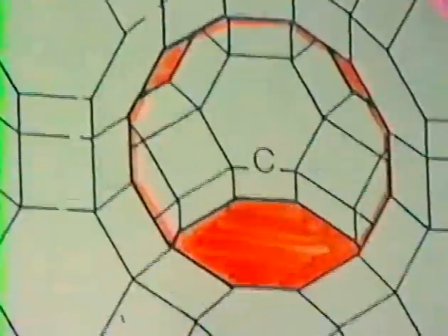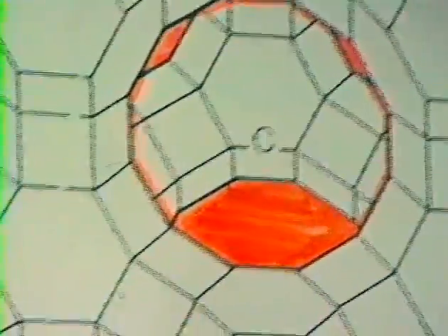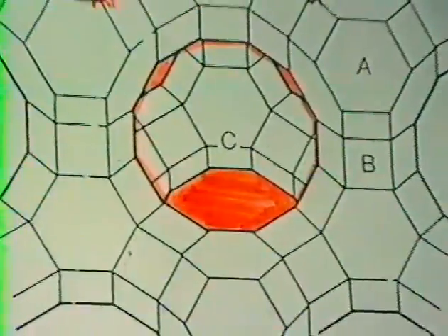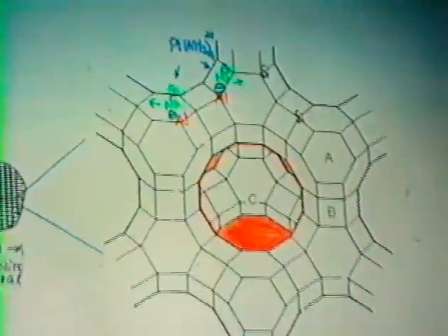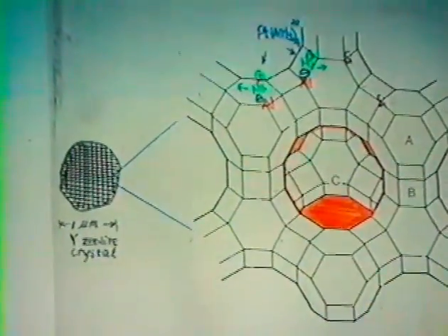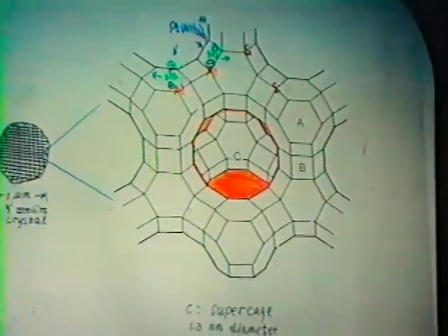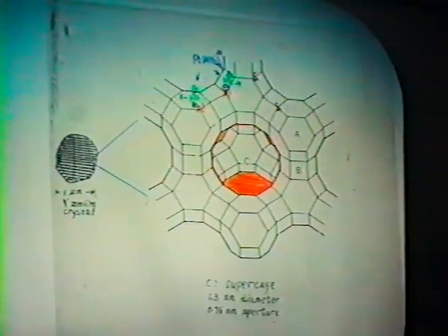Even a single monometallic cluster is very difficult to prepare inside here, but further putting two kinds of metal atoms at the same time in the same supercage will be even more difficult. But the preparation method is very simple. We just ion exchange two different metals simultaneously or one after another, and we evacuate or calcine, and finally we reduce to obtain the metal particles.